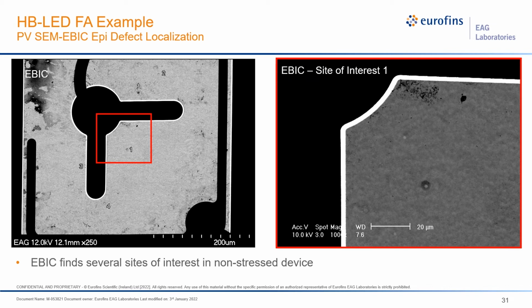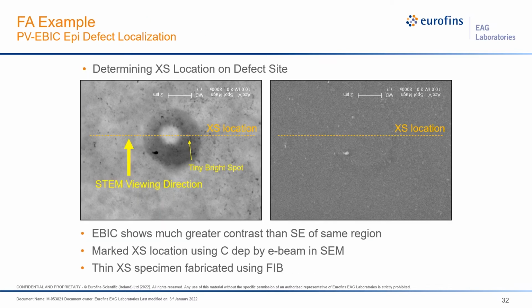So like I said, we should look a little bit closer at this type of defect that we're seeing here, this signature in EBIC. And if we do zoom in on it, we actually see that we have this very bright spot with a dark ring around it. And it's got some hexagonal quality to it actually. So it looks like there's some crystallography involved, which is very interesting. And then we have this very bright spot just to the right of that.